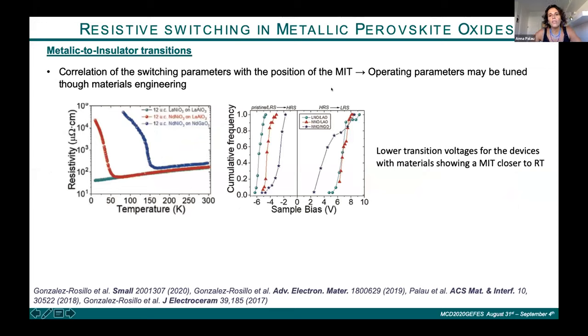Another thing that we can control with these materials is the possibility to correlate the switching parameters, for example, the voltage at which we have the transition, with the position of the metal-insulator transition of the material. For example, in this experiment here, we have evaluated three different nickelate layers with different metal-insulator transitions localized at different temperatures. With these three systems, we have evaluated the switching performance, and we have been able to correlate the lower transition voltages with the material that has the metal-insulator transition closer to RT, which gives us the possibility to tune the material in order to tune the performance of the device.